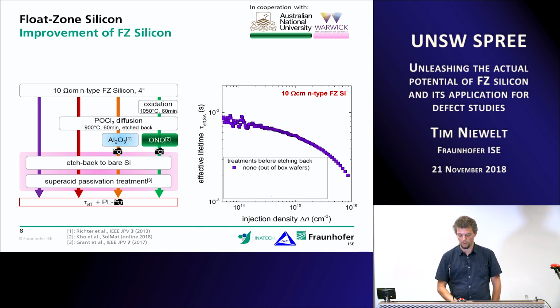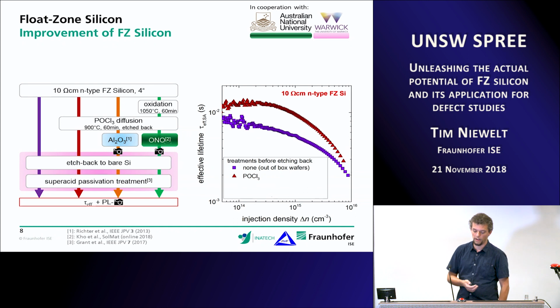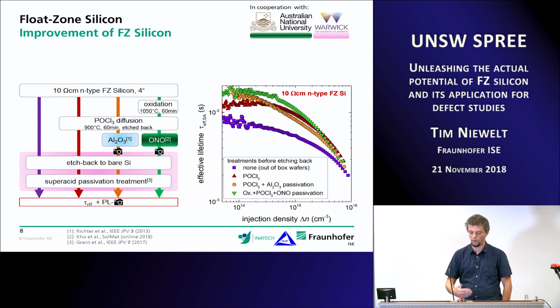So here's some of the results. The initial wafers just etched back and passivated have a reasonable lifetime, I would say. The lifetime increases significantly when the samples undergo a POCl3 diffusion, which is something that you wouldn't usually expect for a float zone wafer, because POCl3 diffusion, yes, we all know that it's gettering impurities, but there shouldn't be any impurities in float zone wafers. The lifetime level doesn't change too much with the aluminum oxide deposition. And what we've seen in a lot of experiments, and this is just one example, is that all the process sequences that were including the oxidation treatment usually gave the best results in such comparison experiments.